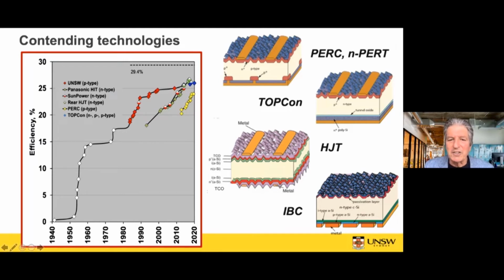A heterojunction structure. Amorphous silicon is generally prepared for solar with about 10% hydrogen included, and that changes its electronic properties. So it acts like a wider bandgap semiconductor than the crystalline silicon. So that allows you to use some technology like III-V heterojunction type technology to form the front and the rear contact, giving you that electronic asymmetry through these deposited amorphous silicon layers.